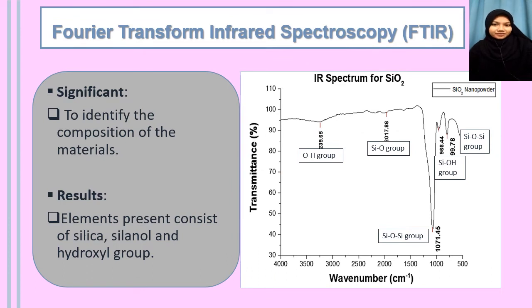Okay, for the result part. First, silicon nanoparticle is characterized by using Fourier transform infrared spectroscopy. The significance of FTIR is to identify the composition present on the silicon nanoparticles. So from the result, it can be seen that the elements present consist of silica, silanol and hydroxyl group. The silanol and hydroxyl have an OH interaction. Due to that, it will contribute to the hydrophilic properties.